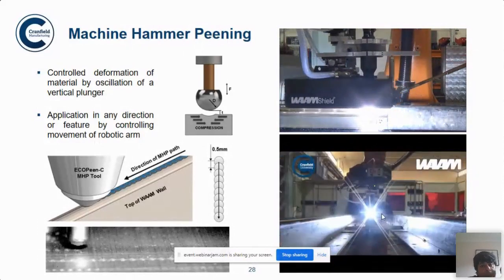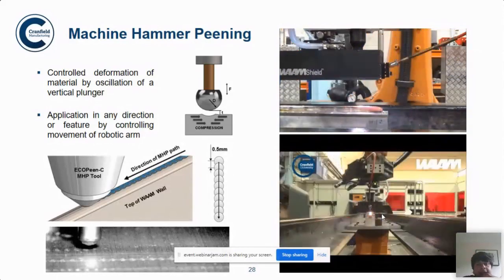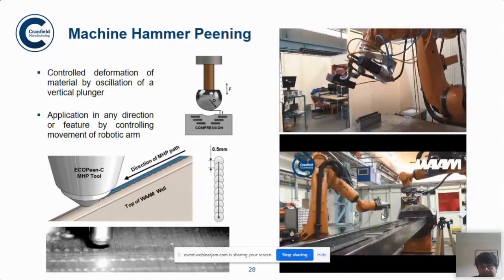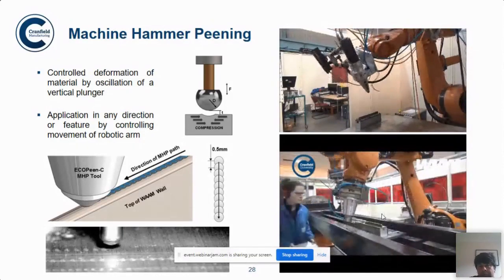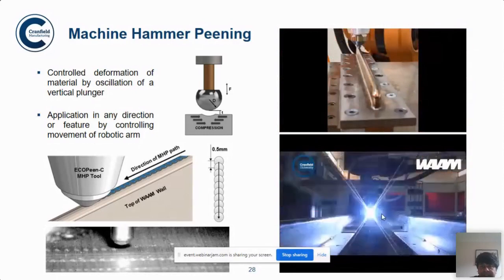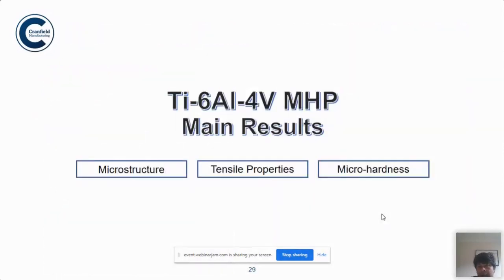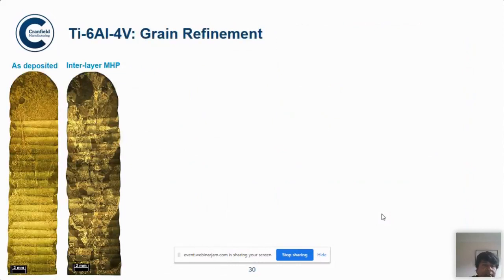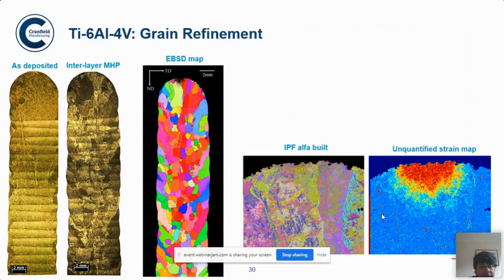So what happens when you peen? You form compressive stresses, and when the next pass is deposited, you basically manage to get a sort of recrystallized layer. A work was done on titanium 64, which is one of the main alloys we produce by the WAAM process. As you can see here on the left, it is the columnar grains. The next picture is interlayer machine hammer peened, which is the EBSD map, and it gives you complete high angle grain boundaries, as you can see, with a very nice structure.